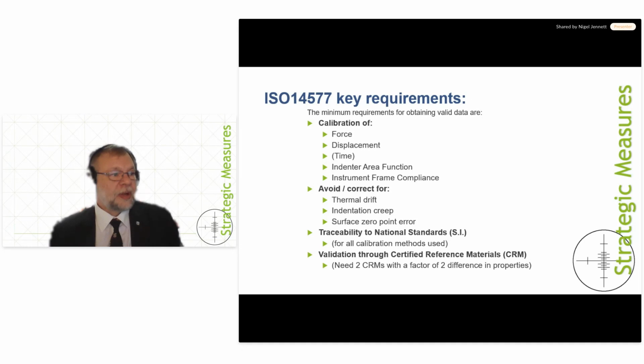That's the whole principle of instrumented indentation: using the area function and instrument frame compliance. And then when you make a measurement, with all of those things set up, they are fixed. But for each indentation you do, you've got your environment at your sample, and you then have an individual indentation thermal drift rate. And depending upon what you're measuring, you could very well have some indentation creep. And as you go to higher temperatures, that's more and more likely to happen, because creep is a thermally activated diffusion process which allows continuous displacement at a constant stress.